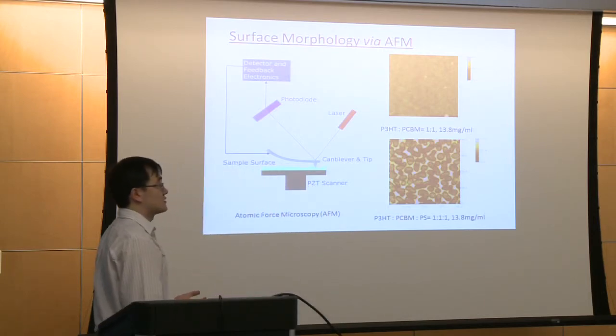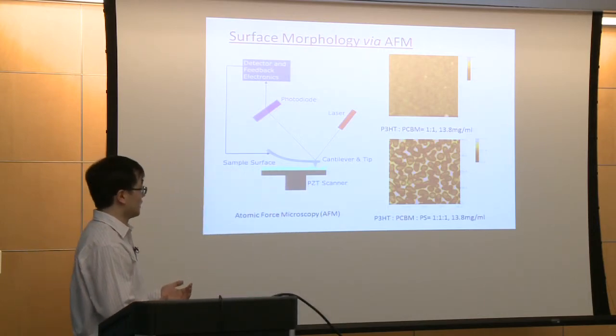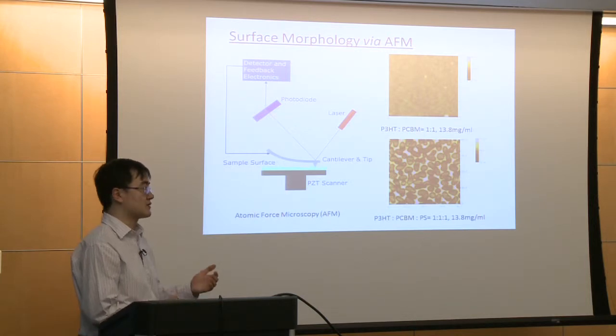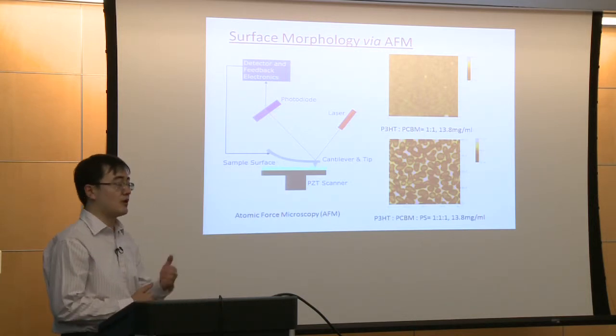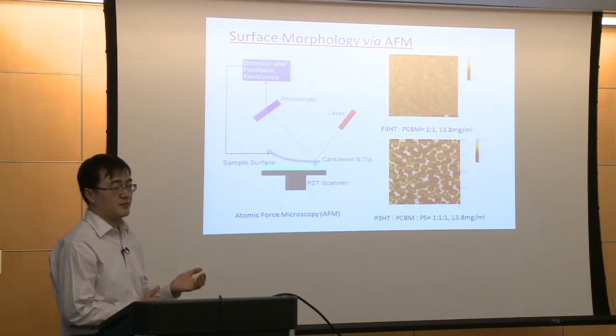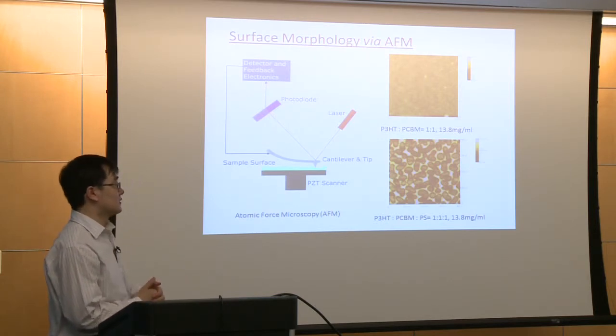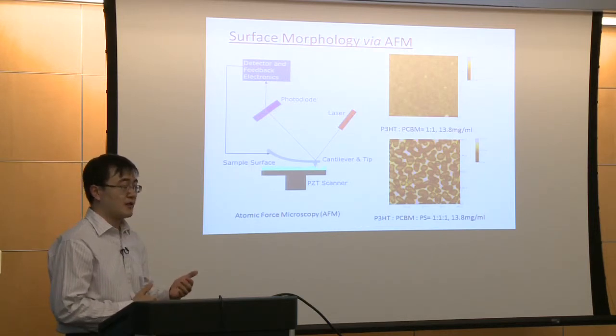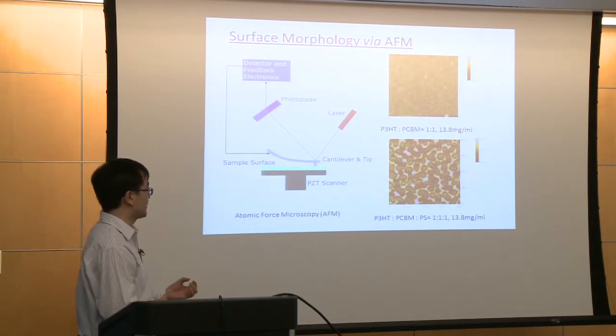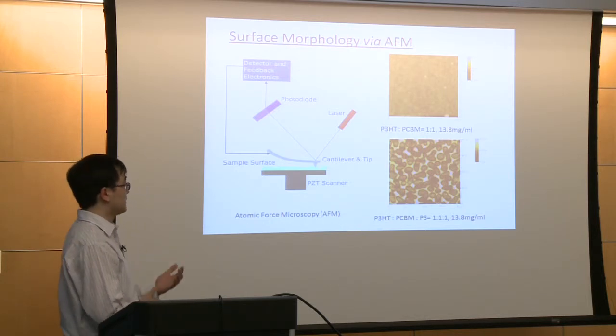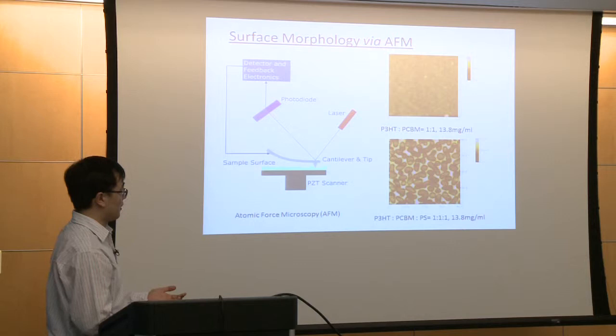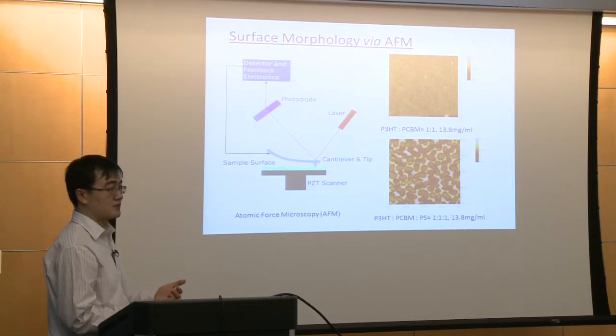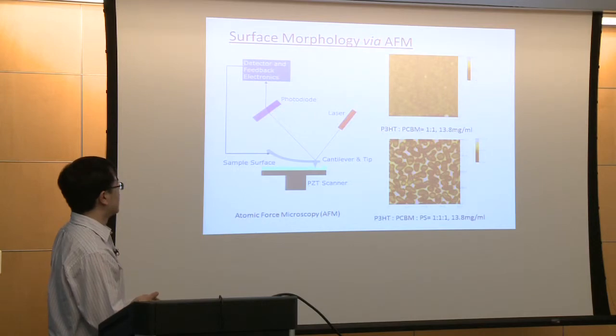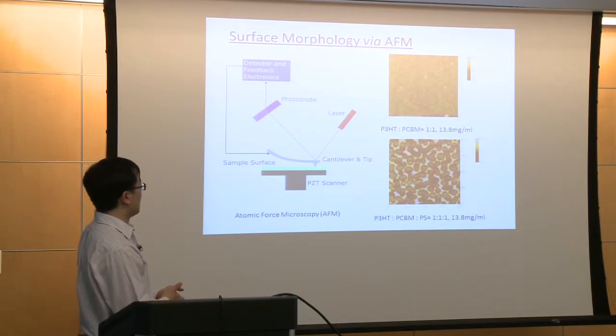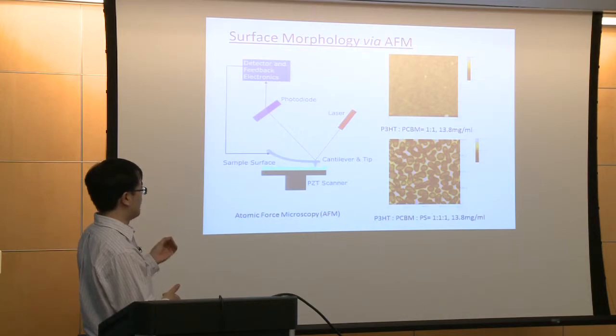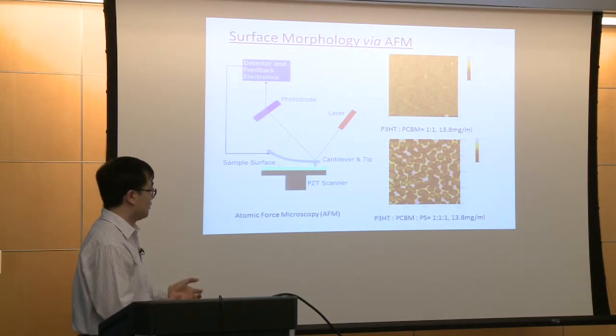Okay, so from the results of the neutron reflectivity, we confirm that there is a repulsive interaction between polystyrene and the P3HT and between the PCBM and the polystyrene. This gives us the possibility to create the column structure and segregate the PCBM along the interface. So then we make some real structures that are very close to the solar cell device. We spin cast the blend film of P3HT and PCBM, or the blend film of P3HT, PCBM, and PS on the silicon wafer.